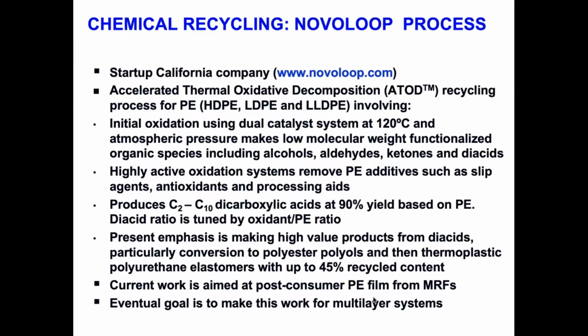Chemical recycling. The second category would be the Novoloop process. This is very new, developed by a startup company in California. It used to be called BioCellection. So accelerated thermal oxidative decomposition for polyethylene of different types. So use dual catalyst oxidation at fairly low temperature and atmospheric pressure, making low molecular weight functionalized organic compounds like alcohols, aldehydes, ketones, and diacids. The oxidation systems are very active. They remove things like PE additives and impurities.